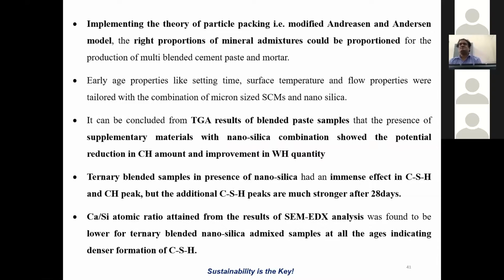From the TGA analysis, what I can understand is that when I'm going with the blended cementitious composite integrated with nanosilica and in the presence of supplementary cementitious materials, it has a tremendous potential in reducing the calcium hydroxide. And it is producing more calcium silicate hydrate. And that is what is going to define my concrete as more durable.